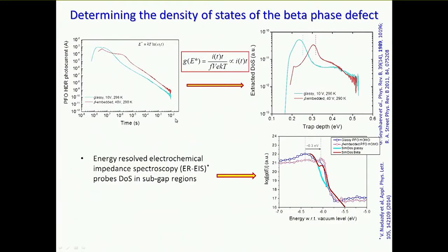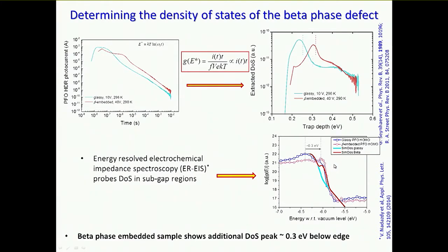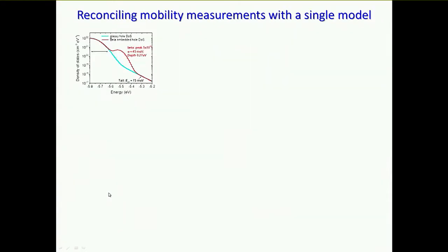We tested it with another method, which a colleague in Bratislava, Wojtek Nadazdi, had developed, an energy-resolved electrochemical impedance spectroscopy, which is a method he could use to look at density of states in sub-band gap regions. And again, he saw a feature at around 0.3 eV below the transport edge, which was present in both samples, but it's stronger in the case of beta phase. So both measurements are telling us the beta phase appears to introduce a feature into the density of states some tenths of an electron volt, 3/10 of an electron volt, below the edge.